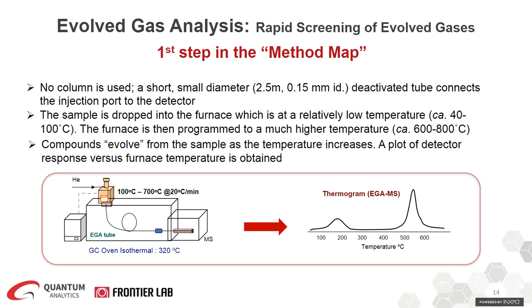Then the furnace is programmed to a much higher temperature. In this example, it's 700. And then compounds evolve from the sample as the temperature increases. So you obtain a detector response versus furnace temperature on the right-hand side. We call that an EGA thermogram. So now using your F-search, you can start analyzing your EGA and even perform more detailed analysis on your sample. That will be the next step.